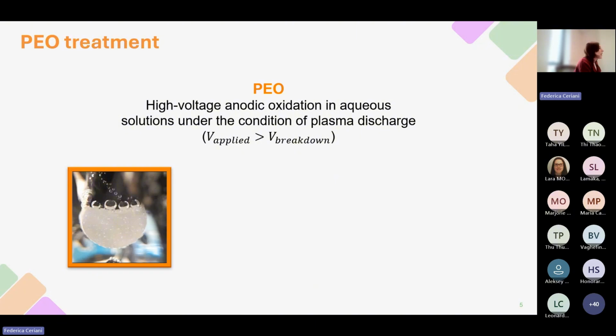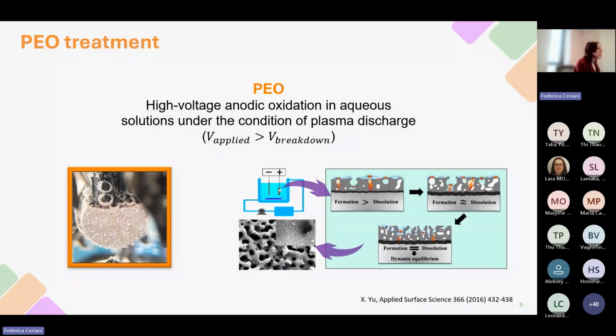To improve the corrosion resistance of magnesium AZ31, it is possible to perform a surface treatment with the aim of producing a protective coating on the surface of the treated component. A possibility is to carry out plasma electrolytic oxidation, named PEO. PEO consists of a high-voltage anodic oxidation performed on a metallic component immersed in an aqueous electrolytic solution, and the treatment is carried out under conditions of plasma discharge, which are achieved when the applied potential overcomes the breakdown potential of the oxide growing on the surface of the treated substrate. As a result of the PEO treatment, an oxide coating is produced on the surface of the treated component.